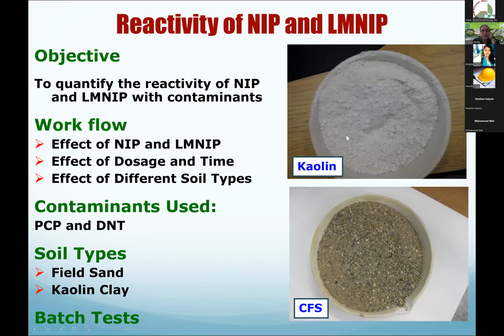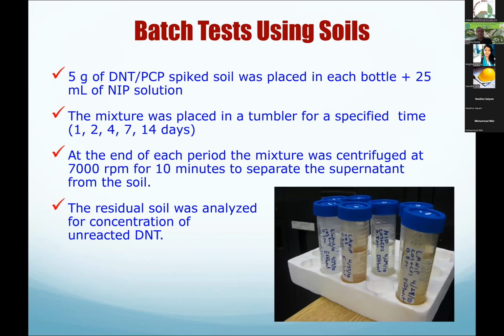So we looked at the kaolin as a low permeability soil, and the coarse sand as another permeable material. So there are the two extremes, low permeability and high permeability soils, and we spike these soils with these contaminants, PCP or DNT, and we look at what is the effect of adding the lactate modified nano iron particles versus nano iron particles. Basically, we do batch experiments, right? Of course, in the field, we want the transport, but to look at the reactivity, we can take the spiked soil and add our solution, nano iron particles or lactate modified iron particles, and mix them, and then analyze the samples at different time intervals.